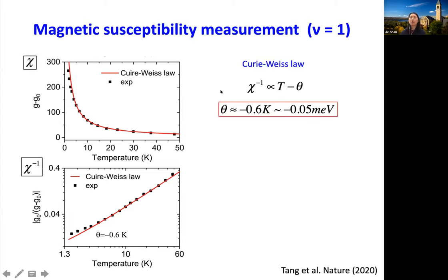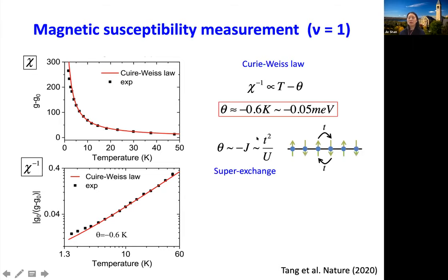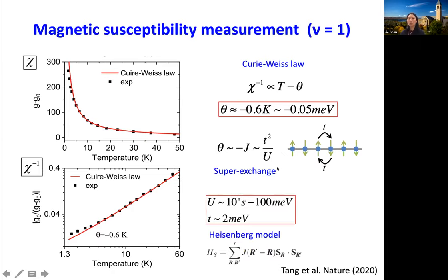The susceptibility changes linearly with magnetic field at low field. After about one Tesla, you get into saturation — all the localized moments are being polarized. Analyzing the slope gives the susceptibility. For filling factor one — our Mott insulating state — we get a Curie-Weiss temperature on the order of negative one Kelvin. If we employ this super-exchange picture for the magnetic interaction — the exchange interaction energy scales as t² over U — from our resistance measurements we already know the order of magnitude for U, and we can infer the bandwidth. Indeed, U/t is pretty big, on the order of 20 in the system.